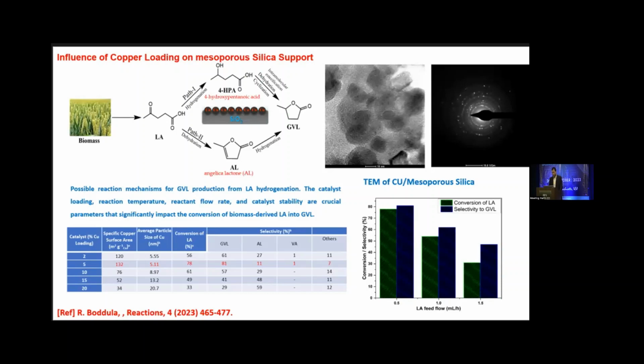We also explore the effect of different parameters like surface area and the particle size of copper, and we find out that by increasing the surface area and decreasing the particle size, higher selectivity and also higher conversion can be obtained. We also explore the levulinic acid feed flow, and it was found that 0.5 is the optimum condition for the feed flow of levulinic acid, with higher conversion and selectivity.